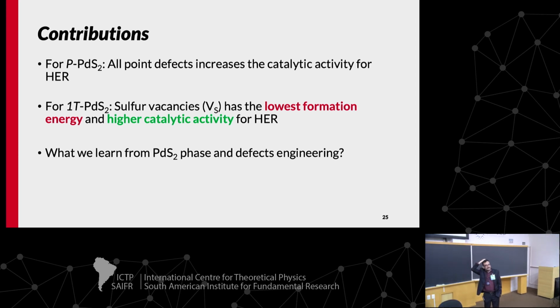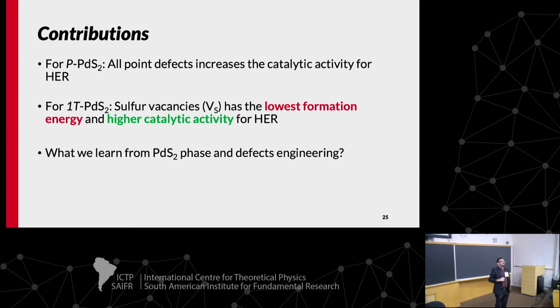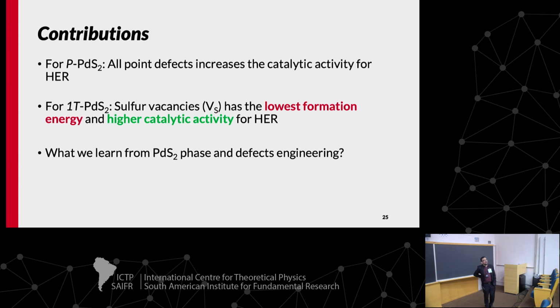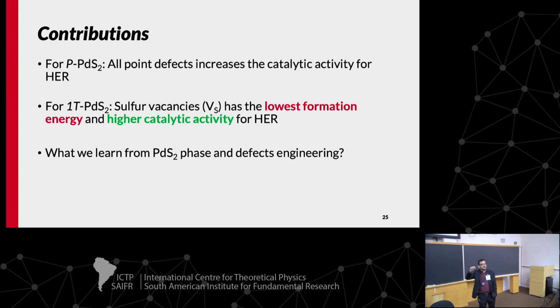That's what I was going to ask. But do you expect very different results if you consider ionized defects or not? I think the charged defect will decrease the formation energy and change the occurrence of this defect. But I don't know if you can extend this to the Gibbs free energy for hydrogen adsorption. Maybe the occurrence of the defects will be very different in this case.